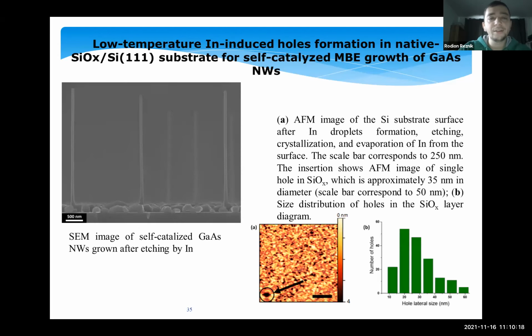So we decided to use not gallium droplets, but indium droplets, because it is much easier to evaporate indium from the substrate, and we have done it. We evaporate indium on the surface with native oxide, then wait some minutes for etching, crystallize these droplets of indium by arsenic, and then evaporate it at lower temperature. And then in these holes we form gallium droplets, and have grown these beautiful gallium arsenide nanowires with the homogeneous diameter